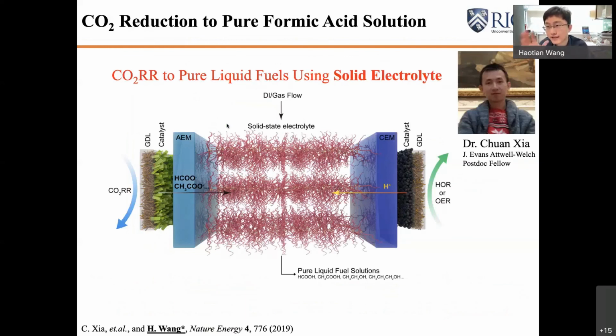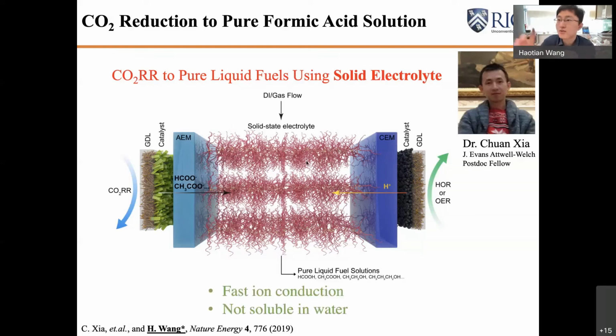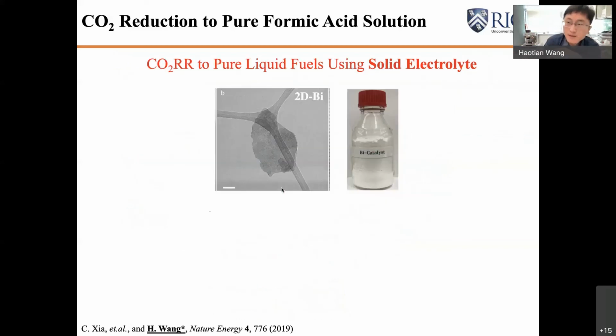So with that motivation in mind, we borrowed a lot of the idea from the solid state electrolyte in the lithium-ion battery field. If we can make a porous solid electrolyte layer between the cathode and anode, we might be able to solve the product mixture problem, because the solid electrolyte can still maintain very good ionic conductivity between the cathode and anode, but at the same time, it won't dissolve in water. So once the formic acid is produced and crosses the anion exchange membrane into the middle solid electrolyte layer, by slowly flowing deionized water, we can easily take out the generated formic acid without mixture with impurity ions.